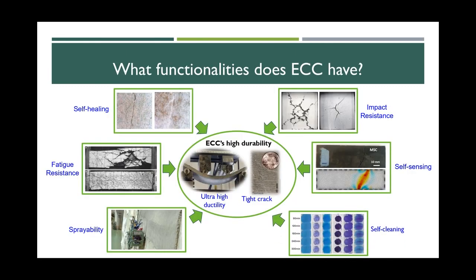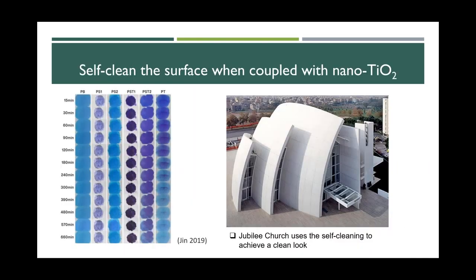And lastly, it has self-cleaning properties. So what do I mean by self-cleaning? Self-cleaning is when you see those ones. This one is with titanium dioxide. So by using titanium dioxide, you can clean the surface of concrete. This one is without titanium dioxide. So those are chemical and also organic dye. And when you use titanium dioxide under UV light, which is from the sun, you can digest those dirts and it can just die down to 0.